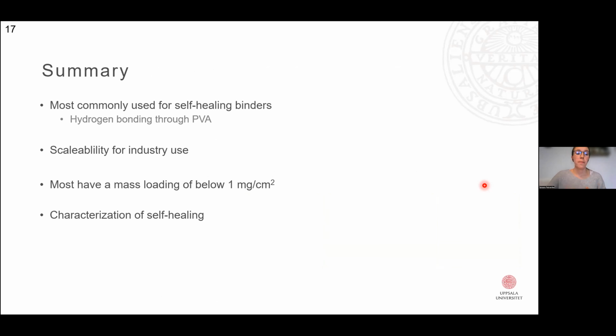So to summarize, the most commonly used self-healing binders for silicon anodes are based on hydrogen bonding through PVA. It's also important to start thinking about the scalability for industry use of these binders, because often around 20 weight% is used in the electrode, and that is way too much for anything that the industry would be interested in. Also, the mass loading is often below 1 milligram per square centimeter, which is very low. So we need to find a way to also increase the capacity of these electrodes.